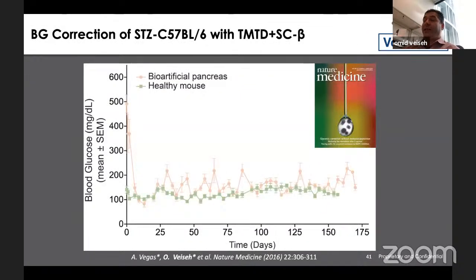And so we wanted to do, I guess, the killer experiment, which is, can we cure a diabetic mouse for the duration of its life, essentially? A diabetic mouse usually lives around 6 months. And so we did this study, and we demonstrated that we were able to maintain glycemic correction, not as good as a healthy mouse, because there are still some things that are not exactly there, in terms of connection to the nervous system and whatnot.